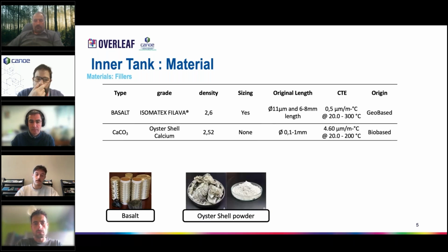Then we tried another type of material, this time in powder form. It's a bio-based one, oyster shell calcium, that we plan to use in order to stabilize the polymers in terms of warping behavior for the crystalline ones. This time the CTE is a bit higher, closer to the polymer, close to 5.